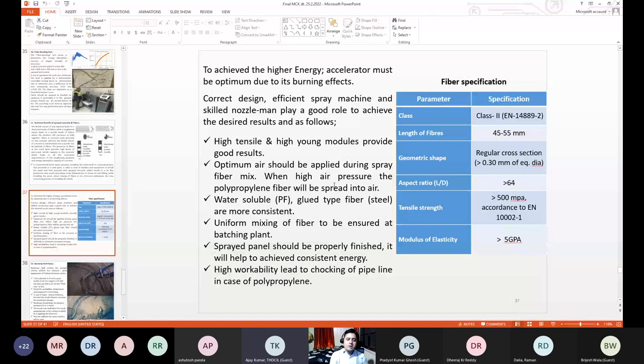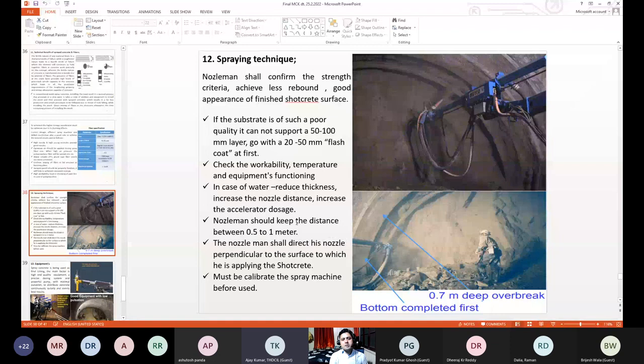Spraying technique. The nozzleman shall confirm the strength criteria, achieve less rebound, and a good appearance to finish the shotcrete surface. If the substrate is of such poor quality that it cannot support a 50 to 100 layer, go with a 20 to 50 flash coat at first. Check the workability, temperature and equipment functioning. In case of water reduction, reduce thickness, increase the nozzle distance, and increase the accelerator dosage. The nozzle should keep a distance between 0.5 to 1 meter. The nozzleman shall direct the nozzle perpendicular to the surface to which he is applying the shotcrete.